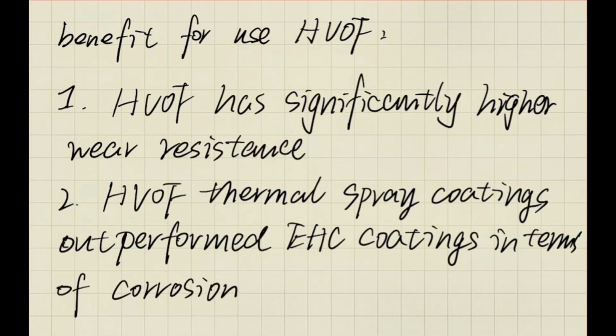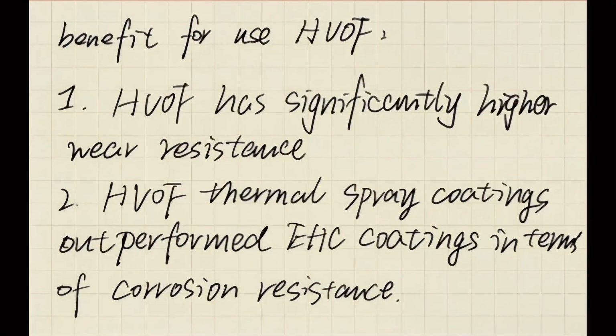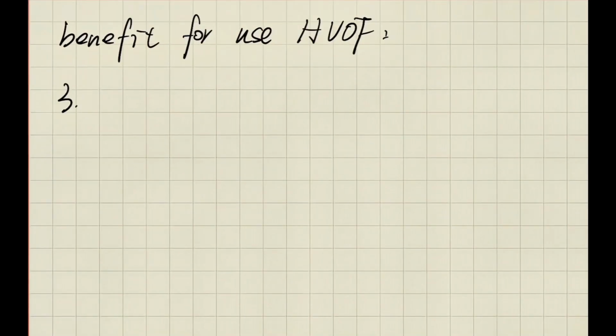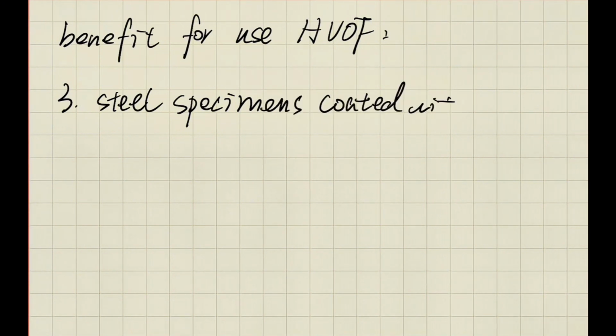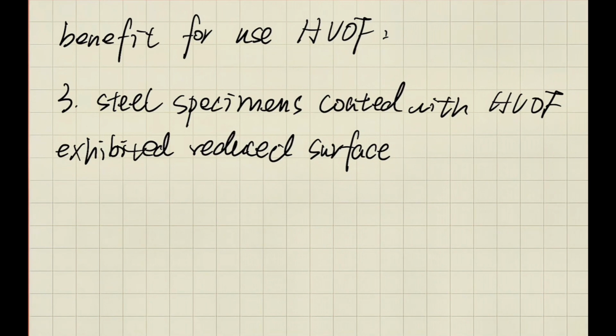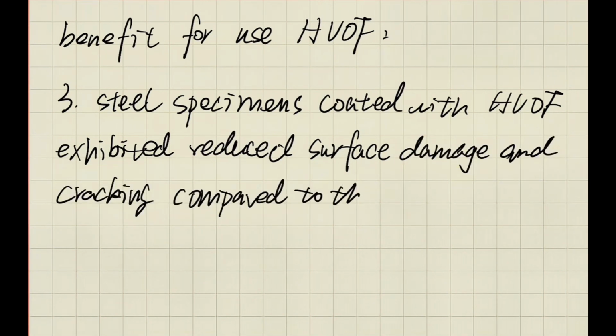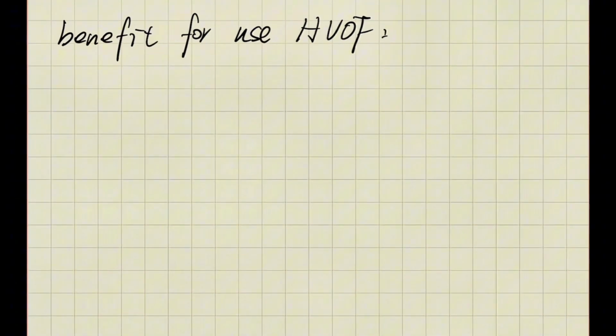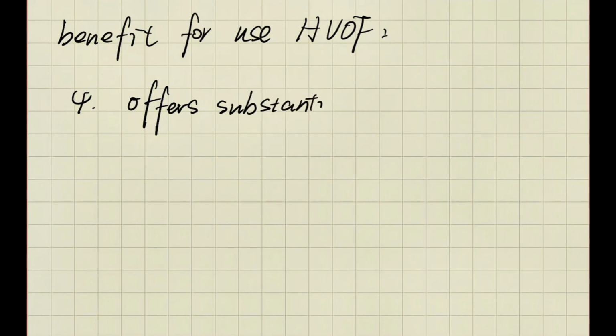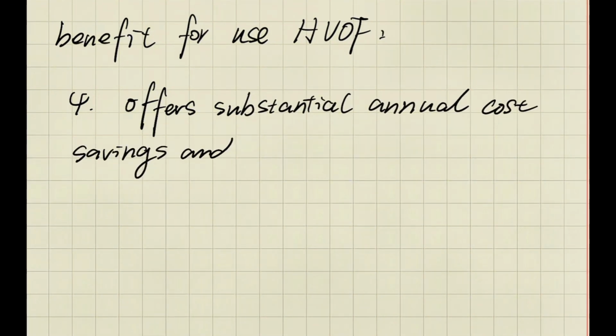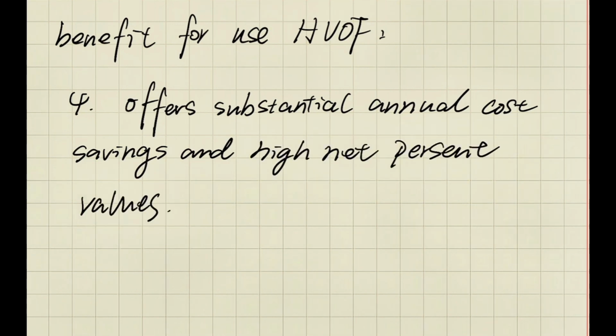Second, after a 3-year corrosion assessment, it was found that HVOF thermal spray coatings outperformed EHC coatings in terms of corrosion resistance. Third, steel specimens coated with HVOF exhibited reduced surface damage and cracking compared to those coated with EHC during gravity impact and ball impact tests. Also, while specimens coated with EHC experienced a significant loss in fatigue strength, those coated with HVOF showed improved performance, and a detailed cost and benefit analysis using the environmental cost accounting methodology revealed that HVOF offers substantial annual cost savings and high net present values over a 15-year period.